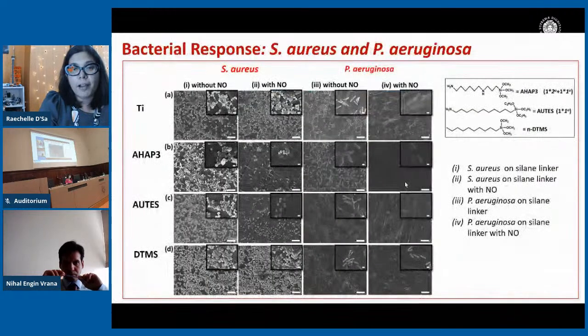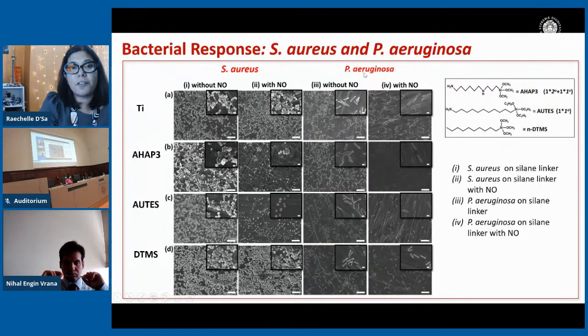But what we found when we looked at the biological response is that we looked at Staphylococcus aureus and we looked at Pseudomonas aeruginosa, which are the 2 bacteria, 1 gram positive and 1 gram negative, that are responsible for most orthopedic infections, is that the surfaces are capable of releasing nitric oxide in a concentration that is bactericidal.